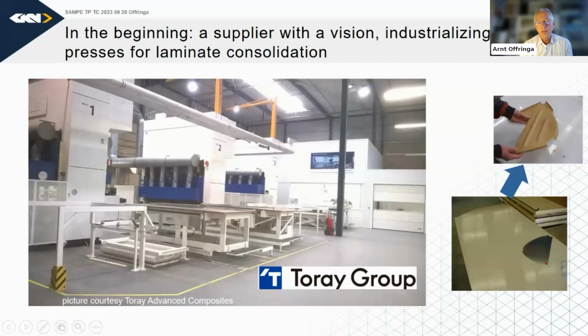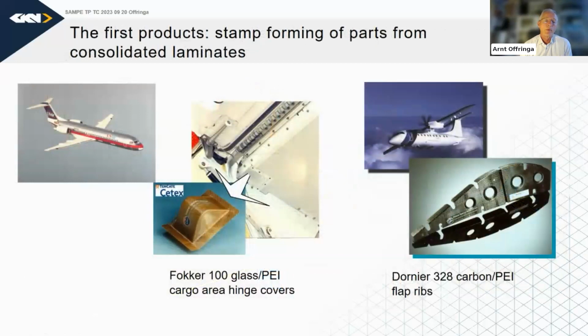And this picture here is of the manufacturing facility for laminates of 4 times 12 feet, 1.2 times 3.6 meters. And we see several presses working in parallel to create laminates. And with these laminates, you can, for example, create stamp-formed parts like ribs. And in the early days, that's what we did in the 1990s. So I started deep drawing and stamp forming for all sorts of aircraft.